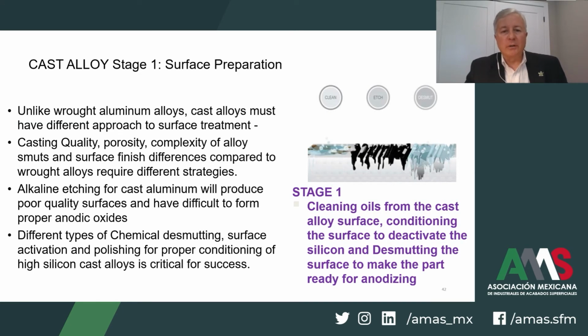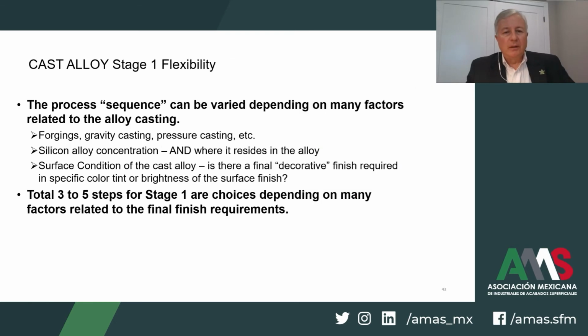As previously noted, cast alloys must have a different approach compared to wrought alloys. The casting quality plays a very critical role in the success or failure. We must avoid traditional alkaline etching chemistries, and the desmutting choices that we use are critical because the complexity of the cast alloy smuts is going to be different than it is for wrought alloy smuts. Some pressure cast alloys require alkaline etching considerations, and compared to gravity casting, we tend to favor acids in that particular application.